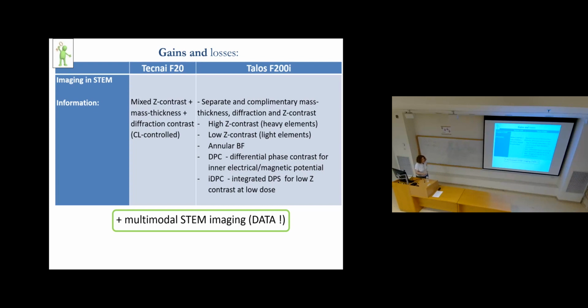What we get with this kind of detection system is a lot of complementary data, a lot of data which was not available before. We acquired the STEM images, but typically what we had in the STEM image was mixed Z contrast, the contrast of the element, mass thickness, and diffraction, and the only way to distinguish between these contrast mechanisms was working distance, so camera length. That was the only way, because we didn't have control over the angles, so we were able to change the acceptance angle of the detector only by magnifying and demagnifying the diffraction pattern on this detector.